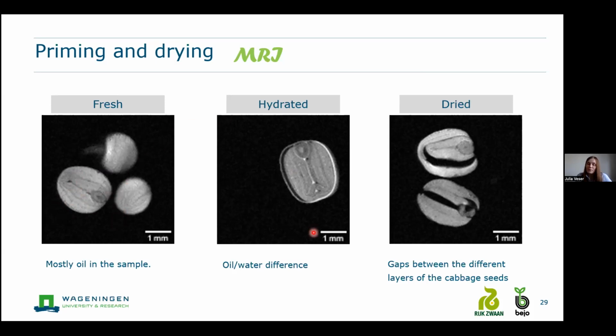In the hydrated one, we of course expect also water. And there's a phenomenon happening here. You see a black line on this side, but not on the other side. That indicates a chemical shift in the signal, which is an artifact because we have protons from two different materials. So we have this oil-water difference, which we see here, indicating that we really see also water. Probably this white line, which should go all around, indicates water. And also in these pores in between, we probably see water.